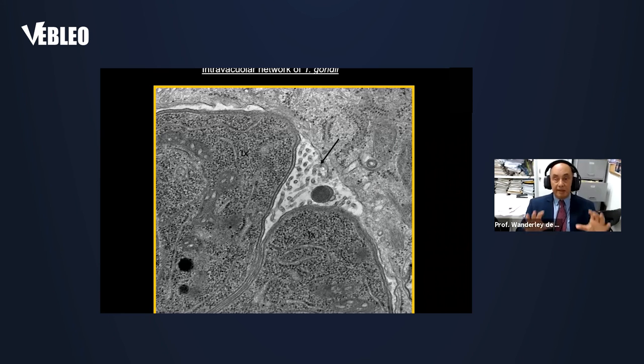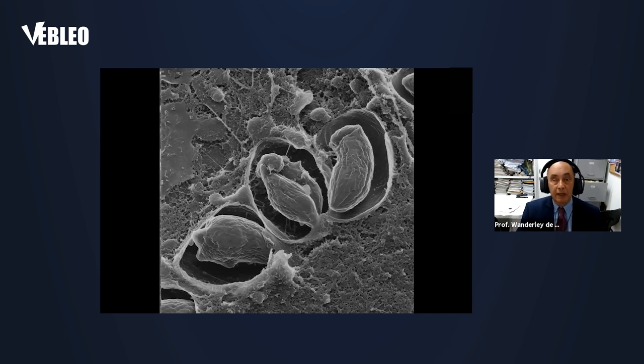And one way to see these inner structures is to expose the inner portion of the cell, so that we have cells that are cultivated, infected with the parasites, then they are frozen or fixed using fixatives such as glutaraldehyde, and then the cells are broken. And then the inner portions of the cells can be visualized. And when you do this, the image we have using the helium ion microscope is like this one. I have here 1, 2, 3 vacuoles. In each one, I have one parasite. We can identify parasite number 1, number 2, number 3 inside the vacuoles. Here is the cytoplasm of the host cells.